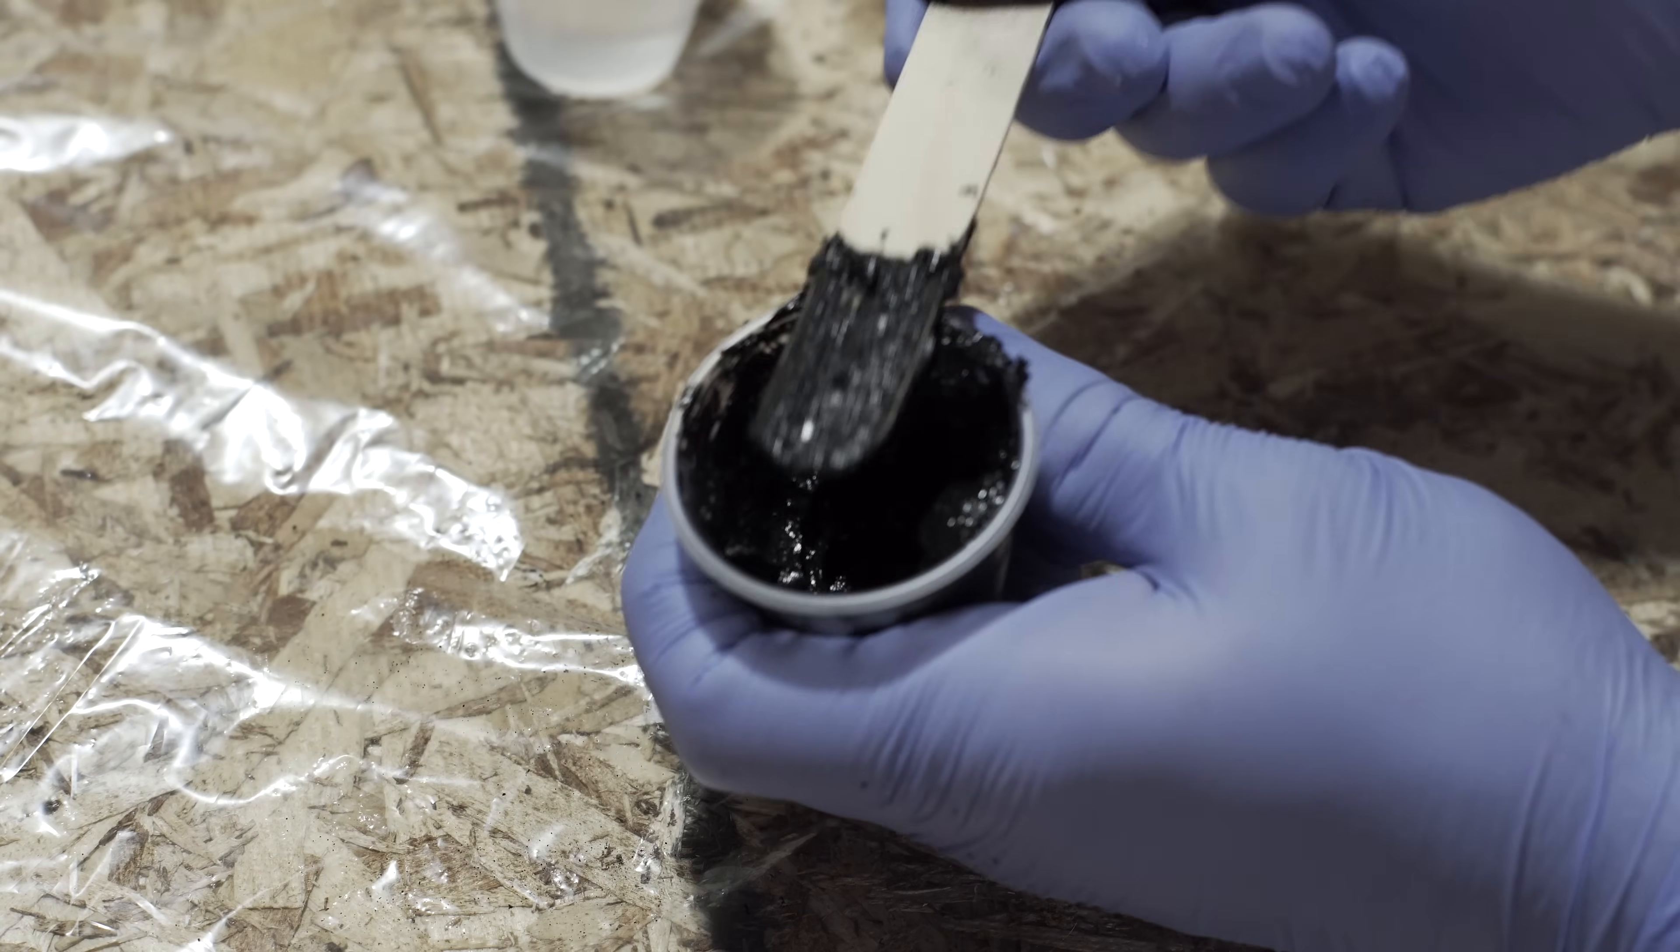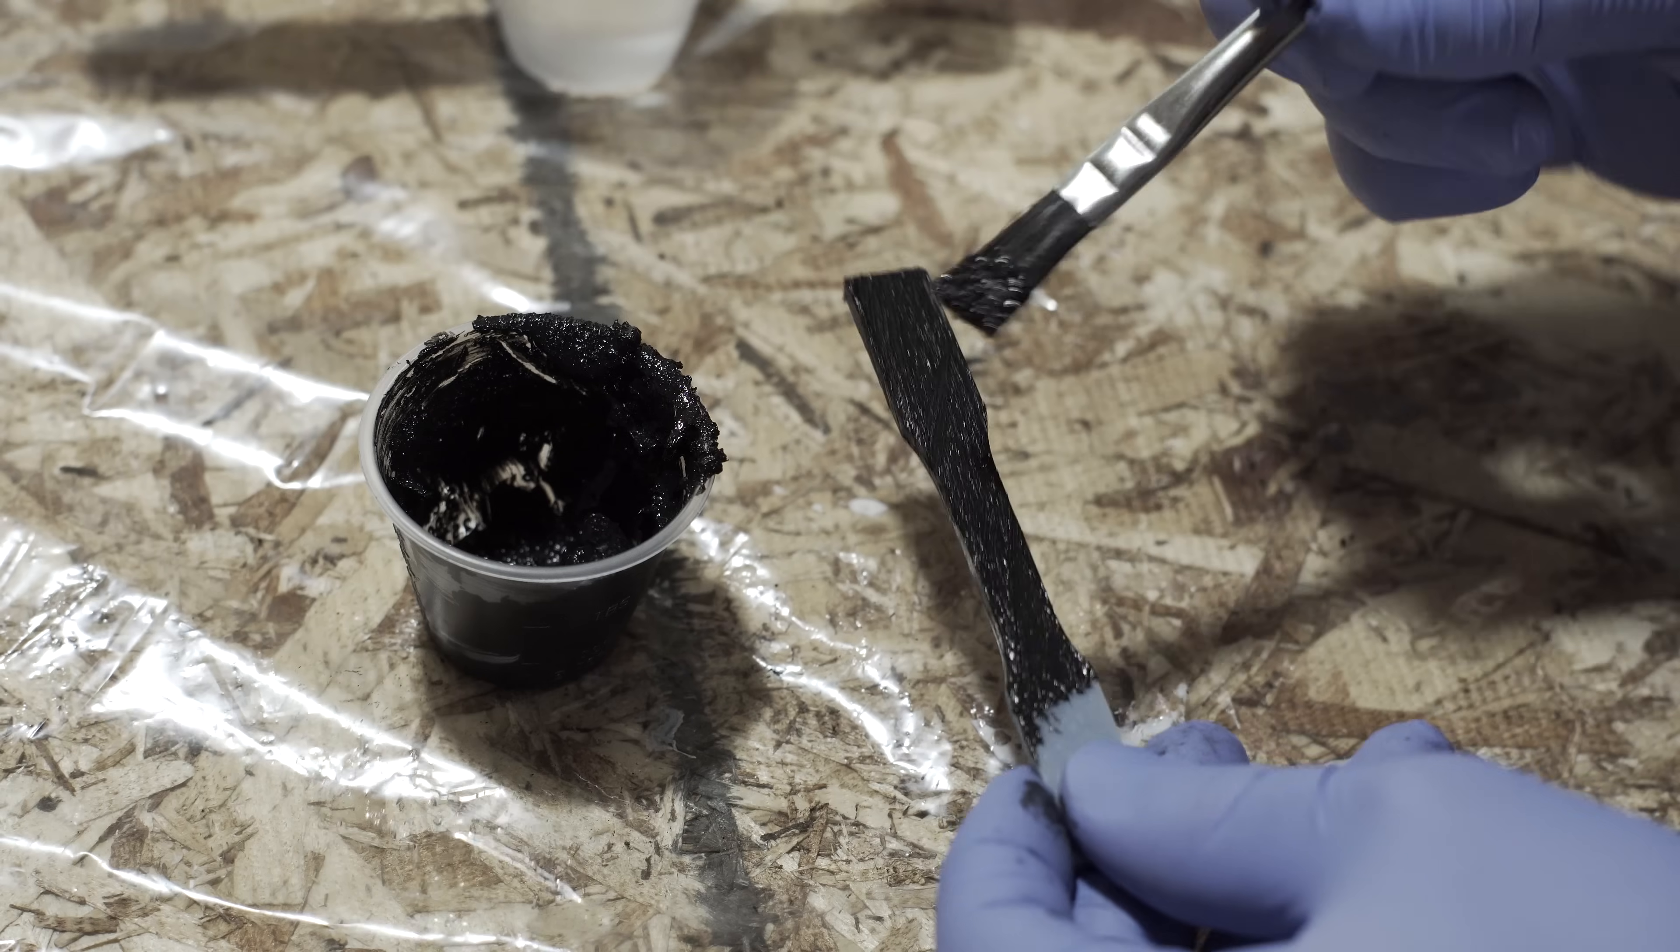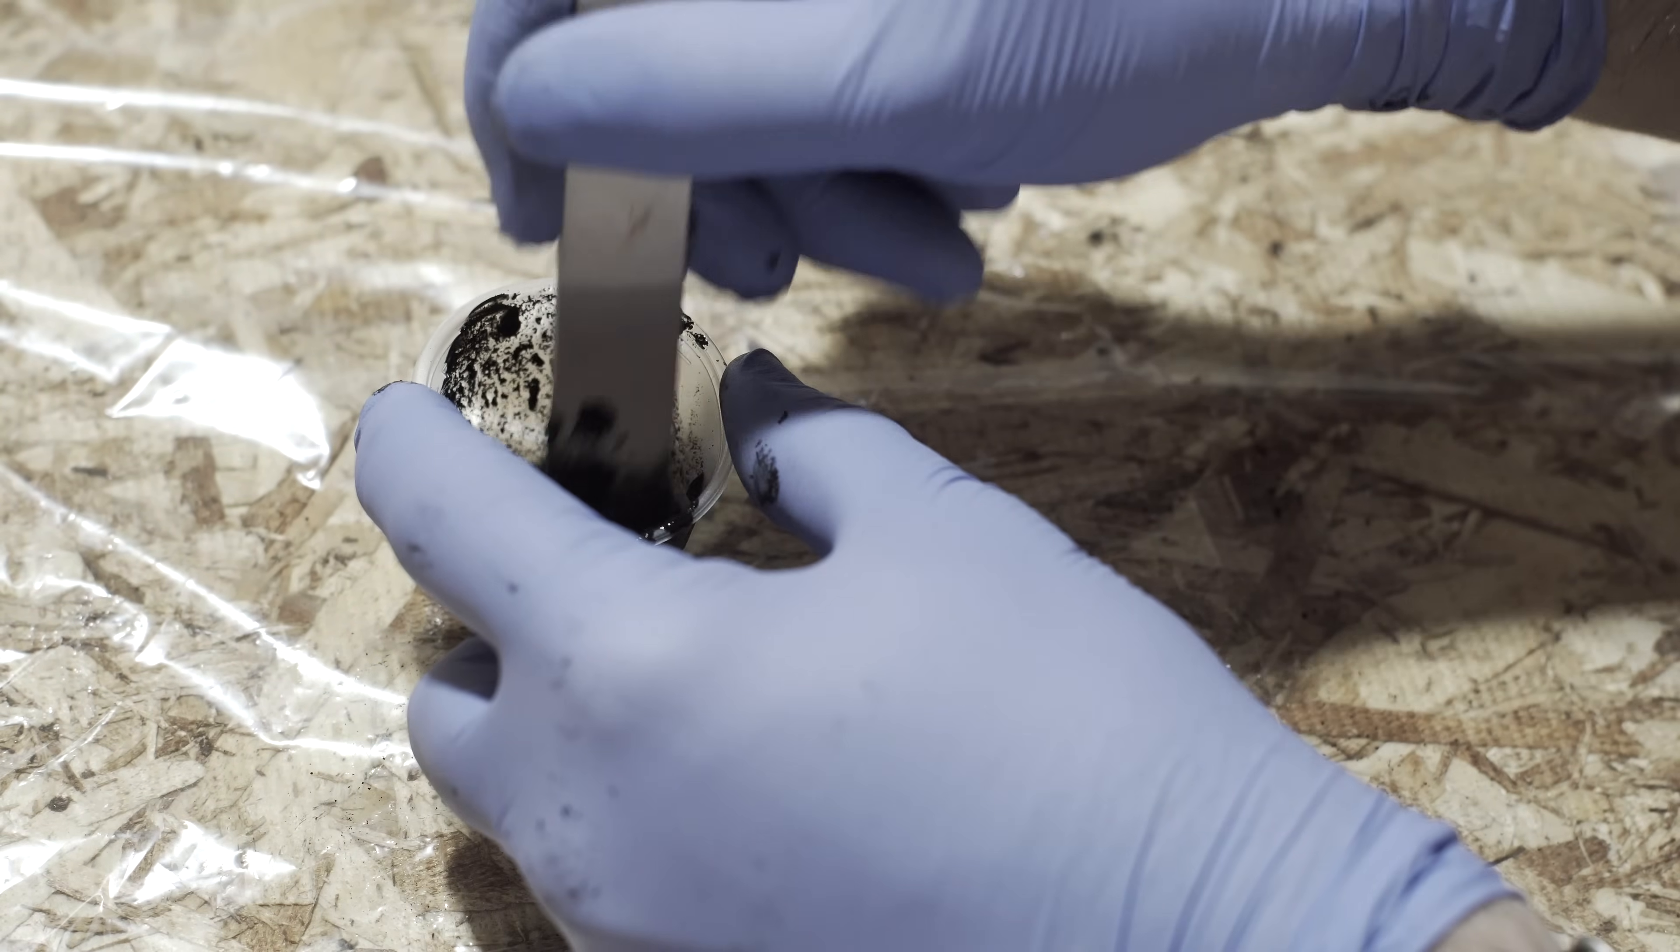I have a resin 3D printer, which I'll be using for this project, but I don't have electroless nickel plating solution. You can buy this commercially. It's actually not too expensive, but it is designed for plating other metals because the metal starts the catalytic reaction. So I'm going to be trying traditional electroplating, which means I need to make the plastic conductive to accept a copper base coat. There's a ton of material on the internet about how to get started with electroplating. And I grabbed the most common method of making plastic conductive, which is making up a conductive paint using graphite. It's essentially a little bit of black acrylic paint to act as the binder, some water to thin it down, and then graphite to make it conductive. My graphite is specifically made to be extra conductive, and it has particles under 10 microns in size. It worked well, but I wasn't really happy with the thickness of the paint, and I feared that it would be difficult to get an even coating across these lattice structures.